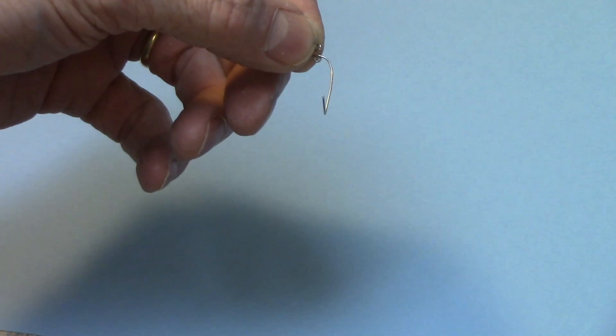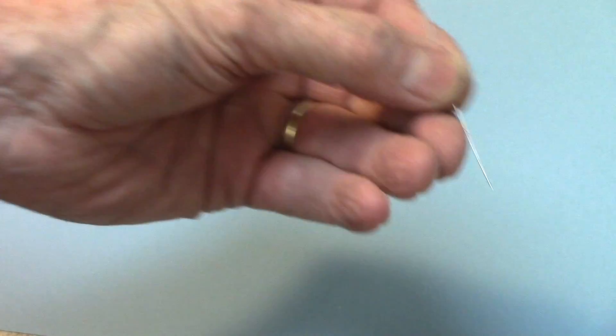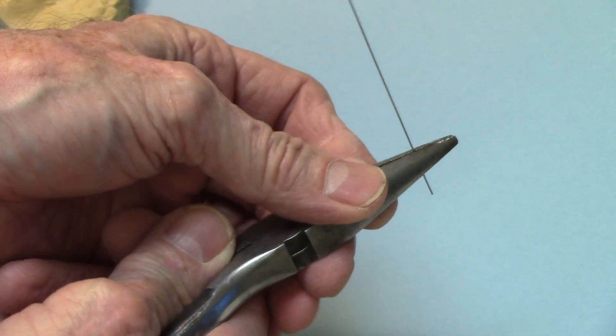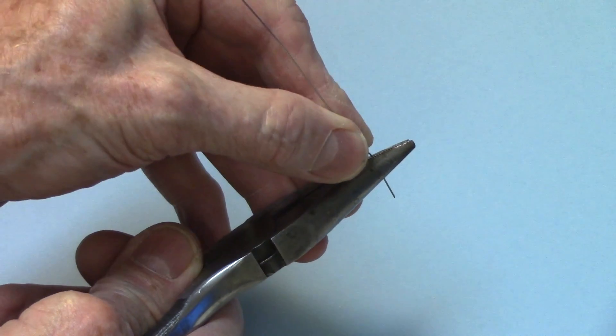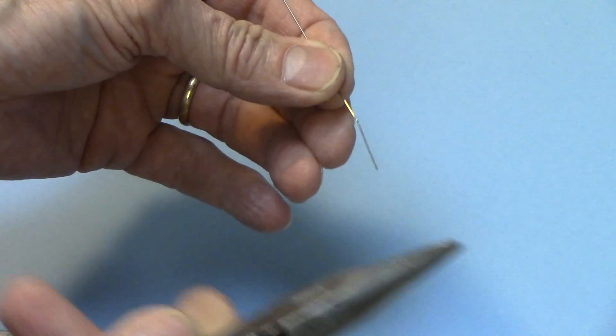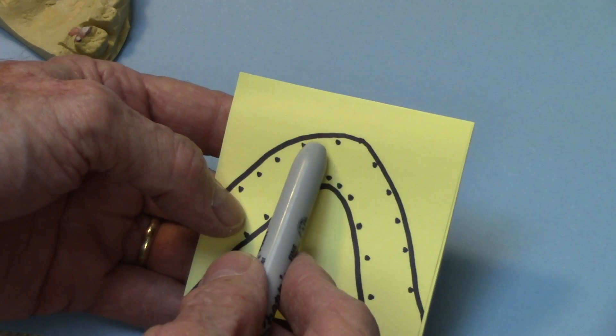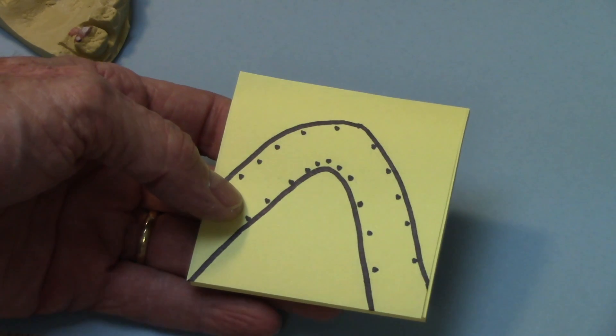What happens there? When you have a wire going into acrylic — let's say the pliers are the acrylic and the wire is sticking out and it's going to be a spring — and you bend it to activate the spring, it's bending right in that one area where it's either soldered or comes out of the acrylic. What that is is the grain structure within the wire is compressed on the inside and stretched on the outside. So if it's a hard bend and it goes back and forth enough times, it's going to break pretty easily.